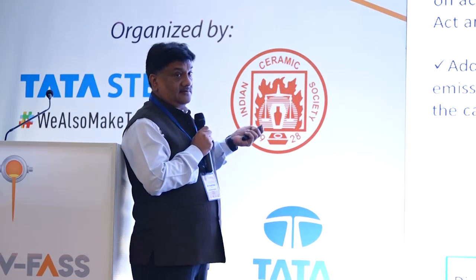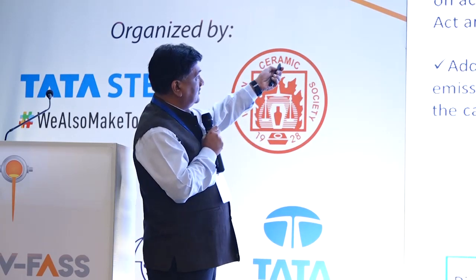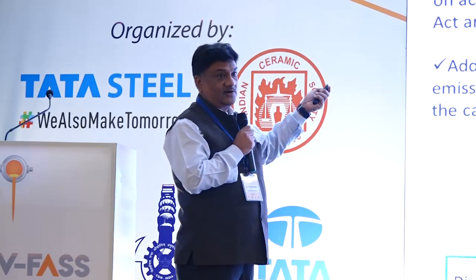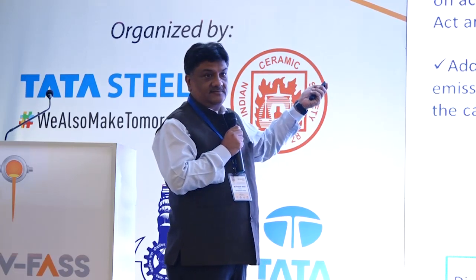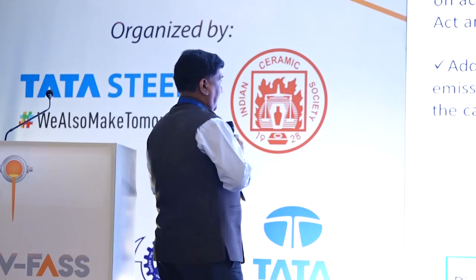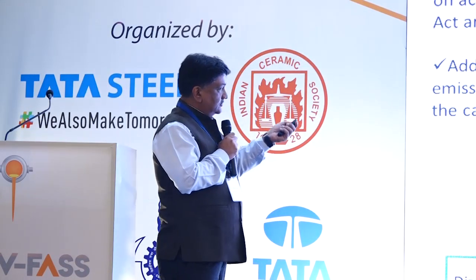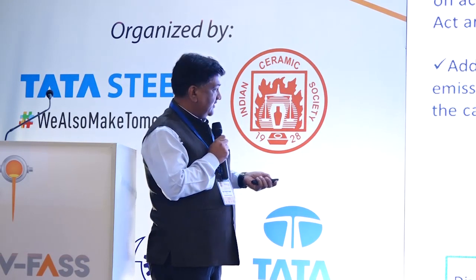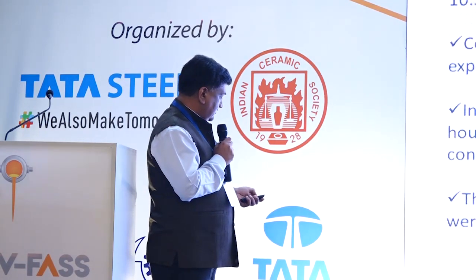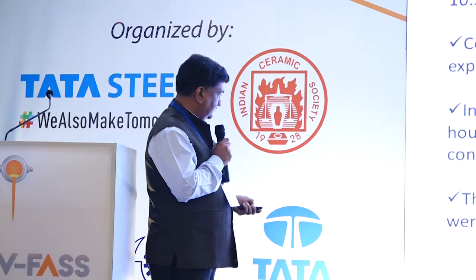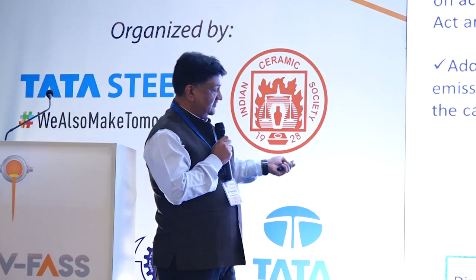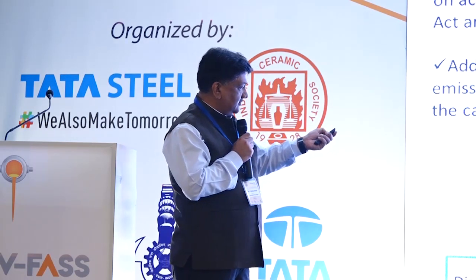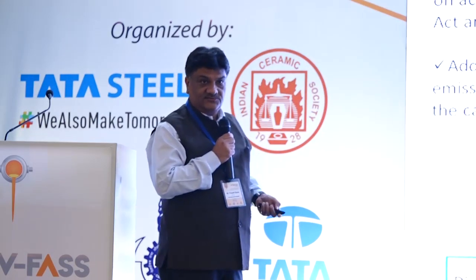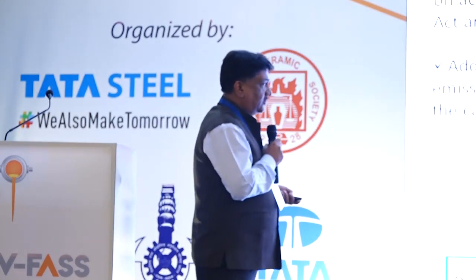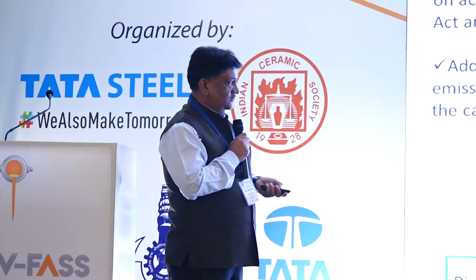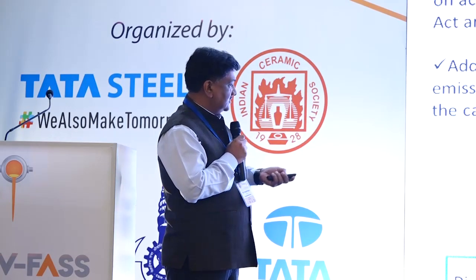But what is the scenario? The scenario is that low LOI fly ash is decreasing worldwide on account of controlling toxic gaseous emission, as per the 1990 Clean Air Act. So we attempted to use this coarse fly ash in our concrete plant, where we had some challenges of decoloration in concrete, poor air entrainment, no retention availability, say 2 to 3 hours, which is required commercially for any ready-mix concrete supply in India, and lower compressive strength. Particle size also put us a lot of challenge to use it.